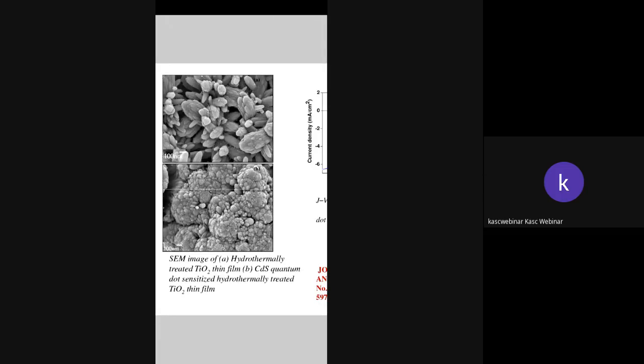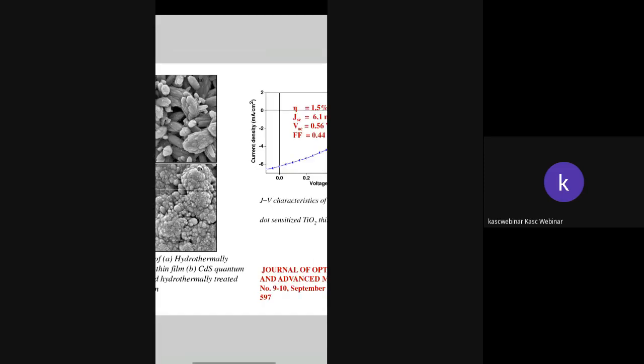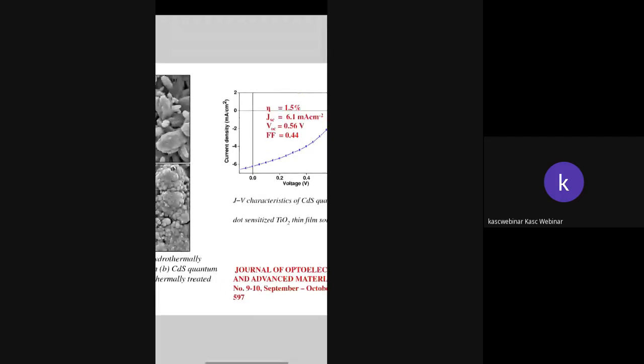In the second image you can see the quantum dots have been well coated over the cactus-like structure of TiO2. The efficiency calculated for this type of hydrothermally treated TiO2 is 1.5%. This result is an indication of enhancement in efficiency when we alter the structure. And even though there are many advantages in third generation solar cells, long-term stability is a challenging issue.